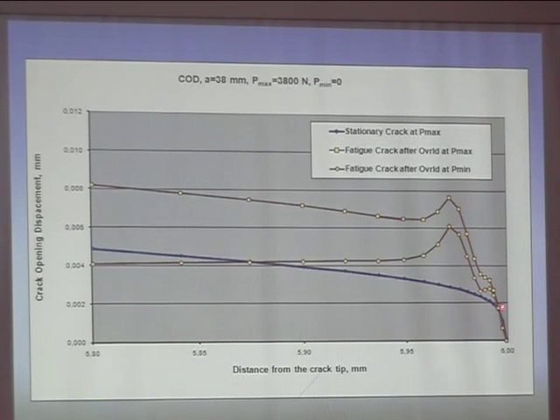And what you see here, in that region, after reaching a certain load level, the displacement was getting a little bit less, but in this region the displacement seems to be the same, they don't move. So now, if you measure relative change of displacement behind the crack tip, you will assume that this is closure, because the opening displacement doesn't change anymore. But that doesn't mean that the crack is closed, according to this analysis.